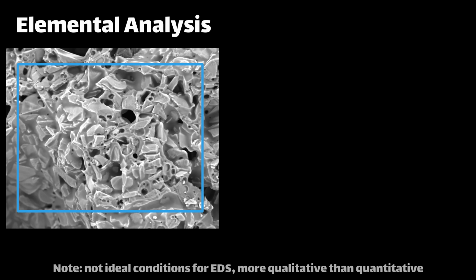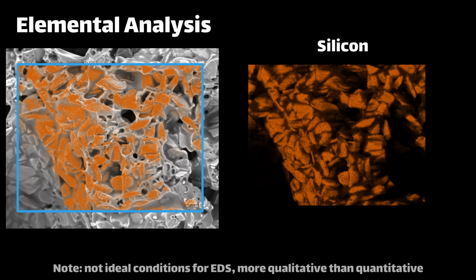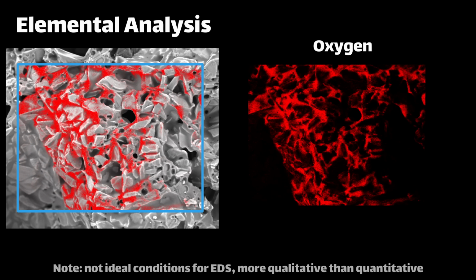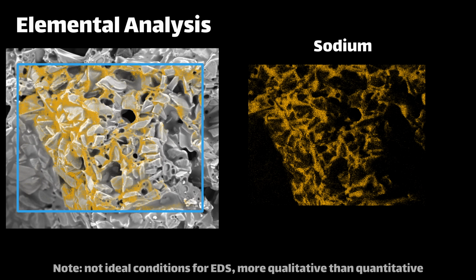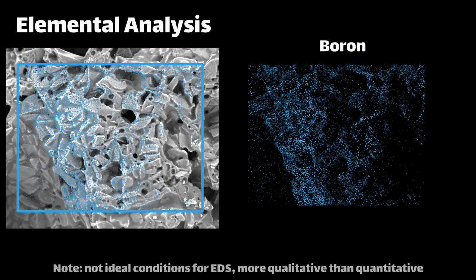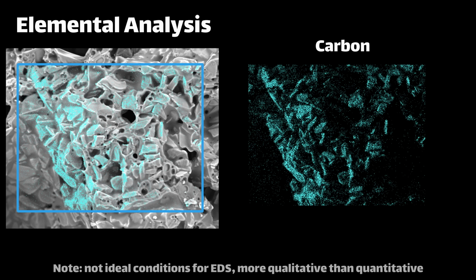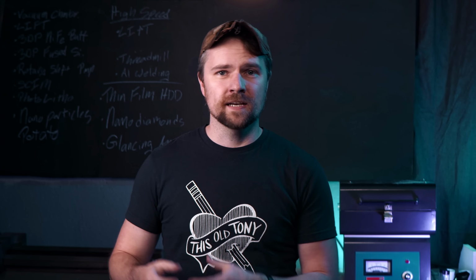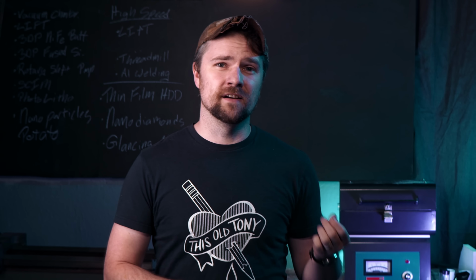And the reason for that is that the oxide layer that's on top of these grains is very thin, so there's just not a lot of silicon dioxide to work with, but there's a whole bunch of boron and sodium from the borax. So whatever glass ends up forming is going to be really borate heavy and silica light. And borate glasses are water soluble. So that could explain some of the variability that we're seeing. The borax washes away immediately in the hot water, and then the glass bridges that are left, the ones that are really strong and robust because that region happened to sinter well, are more resistant to dissolving, whereas other regions that have very light glass networks dissolve away quickly.